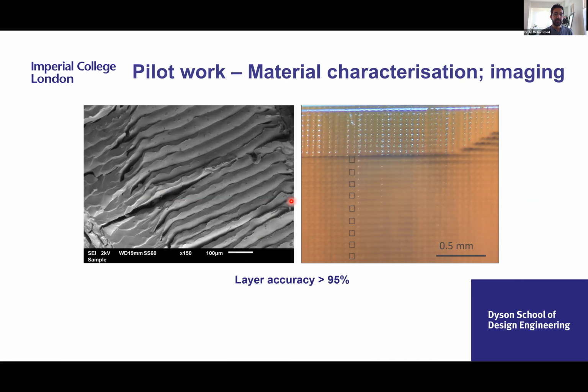Imaging, so here you can see an SEM that we did just to measure the layers and to see if there's any delamination in the print between layers. Delamination would occur like this, but then again, during SEM, you have to freeze dry it. So that could be caused by the freeze drying process. So using an optical microscope, we had a look at the layers and they're within above 95% accuracy of the layer that was intended by the design. So by design, it's 50 microns that we chose per height. And here you can see that it was around 50 microns. It's very difficult to see without an arrow around it, but it's very, very accurate.